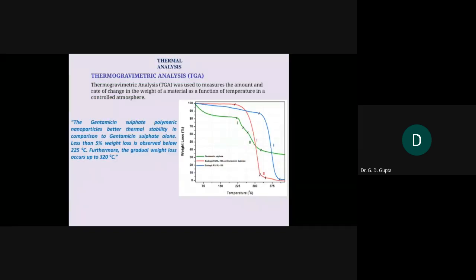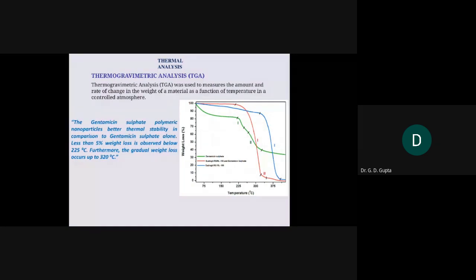Next, thermogravimetric analysis is particularly used to measure the amount and the rate of change in the weight of the material as a function of temperature in a controlled environment. By the graph, you can see that the green line is gentamicin sulfate alone. The red line comprises Eudragit RL, RS100 and gentamicin sulfate, that is the nanoparticle. And the blue line is pure Eudragit RS, RL100.